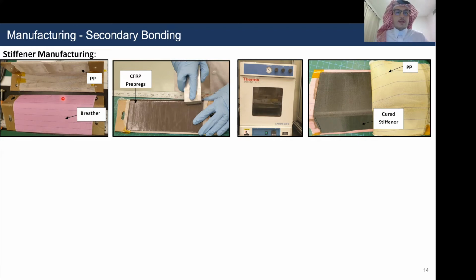A mold was designed previously, which was covered with a peel-ply fabric from one side and a breather fabric from the other side. And the CFRP prepregs were laid up by hand on the mold with the respective quasi-isotropic stacking sequence. They were rolled over with a roller to ensure there are no air entrapments between the plies, once 8 layers of CFRP prepregs were stacked.